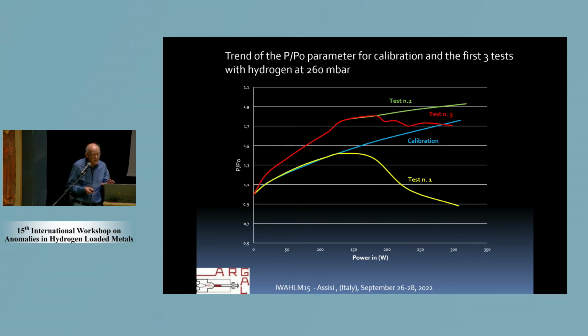This is the normalized pressure, just to compare the pressure that is not always exactly the same at the beginning of the experiment. We operated at about 260 millibar, quite low pressure. You can see here that at a certain power, about 100 to 150 watts, the yellow curve goes down with respect to the reference.